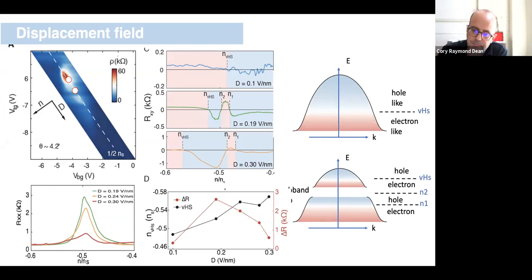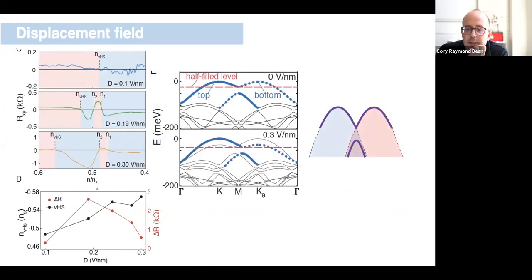Okay, so in our data, we think this tells us that we have a resistive feature that always appears at half band filling, but its strength depends on whether the Van Hove singularity is at half filling or not. So it also necessarily tells us that the insulating state we've identified, a half band insulating state, does not follow the Van Hove singularity. It does not occur where the Van Hove singularity occurs. It occurs at half filling always, but its strength depends on whether the Van Hove singularity is coincident with half filling or not.